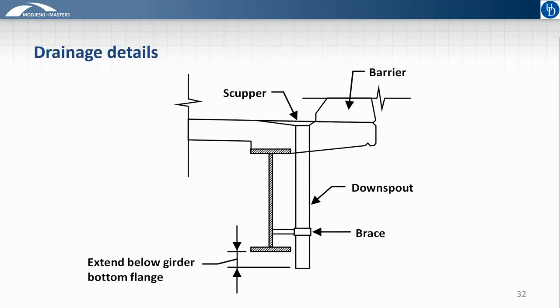Moving into some of the further drainage details, one of the common problems that's been seen in the past is when downspouts from deck scuppers have not been extended far enough below the bottom of steel. Oftentimes a rain event will be accompanied by relatively strong winds that can blow the drainage coming out of the bottom of the downspout back onto the steel and cause an area of continued moisture. And so extending that downspout a sufficient distance below the bottom of steel is important to make sure that doesn't happen. Often a 12-inch distance is used in this area.